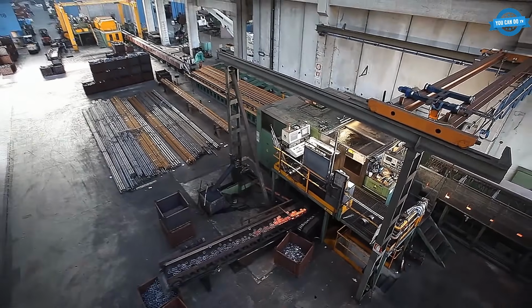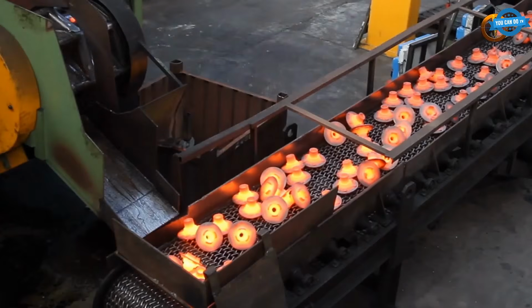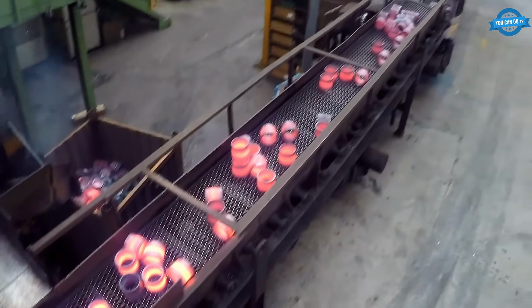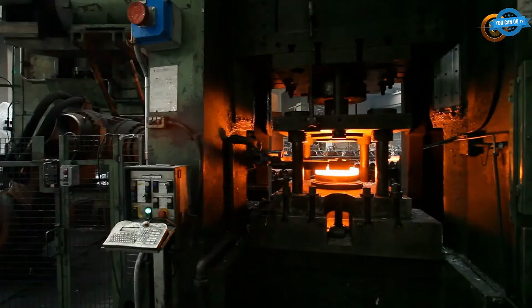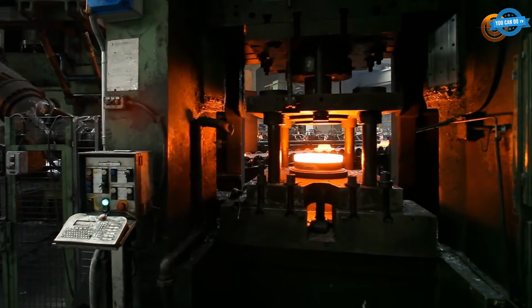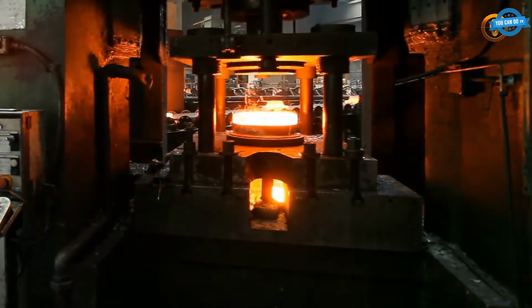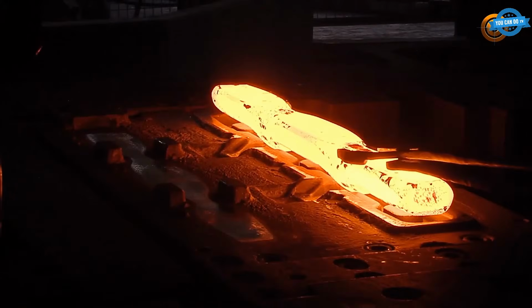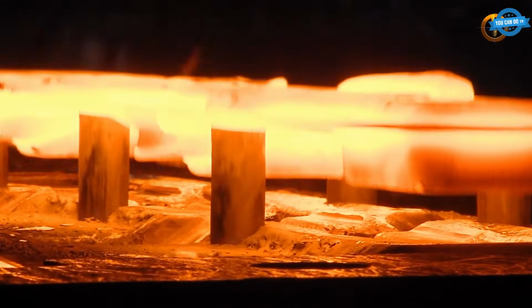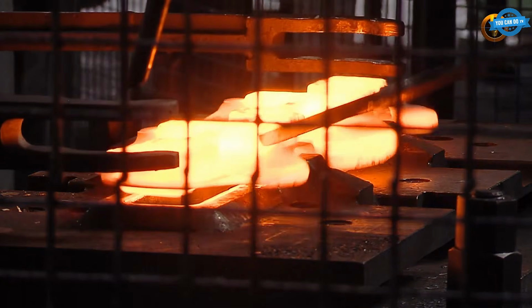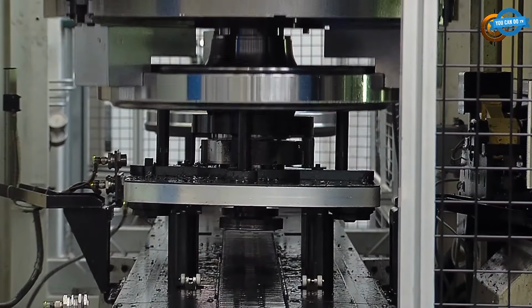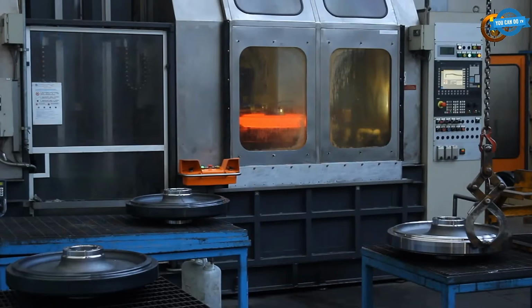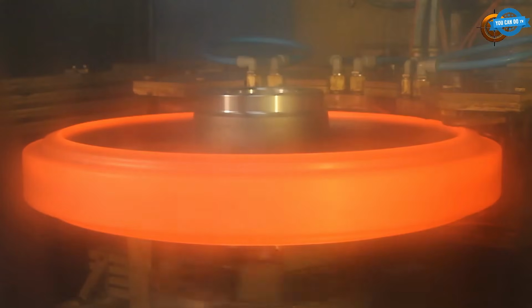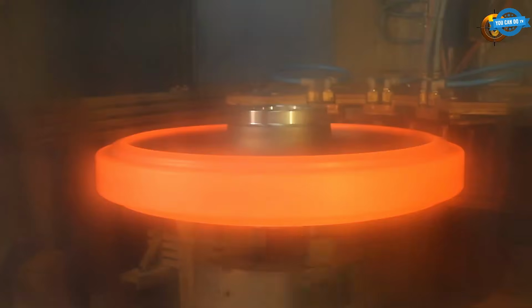And here's what an industrial forge looks like when it's set up to produce large forged components at real volume. Steel billets get heated in induction furnaces to precise forging temperature, then transferred by robotic arm to closed die presses that shape the part in a controlled sequence. Each part goes through preforming, a rough shape. Then, through finishing, dies that press the metal into its final geometry with tight tolerances. Trimming removes the flash, which is the excess material squeezed out of the die parting line during forging. Heat treatment follows immediately. Quench, temper, or normalize, depending on the alloy and the application.